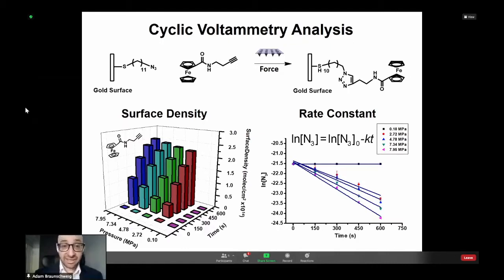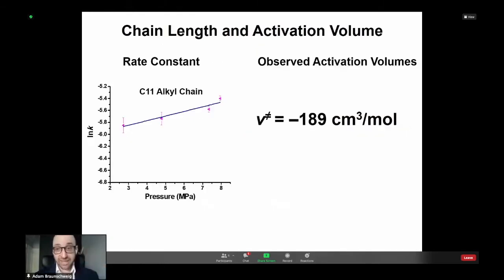And what we could do with these data here is we could apply pseudo first order kinetics and get a rate constant out. Now, if you plot the natural log of the rate constant versus the applied pressure, and you take the slope of that line, what you get out is this term called the activation volume. The activation volume of reaction is an old term that was adopted when people studied reactions in solution but under applied pressure. And the activation volume can generally be thought of as the difference in the volume between the products and the reactants. When the products are smaller than the reactants, pushing them together drives the reaction forward as a result of Le Chatelier's principle.